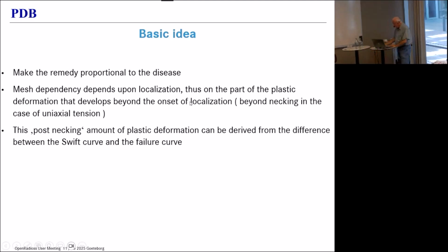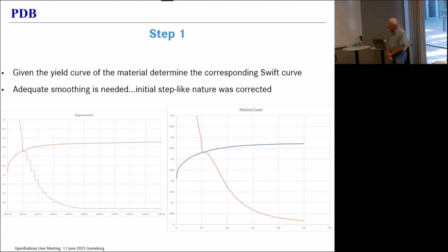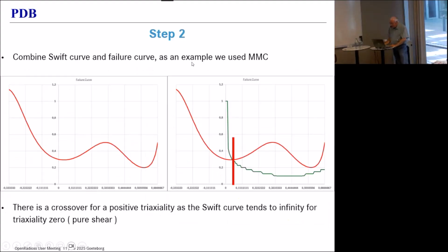So that's a very simple process. In step one, we take our yield curve and we take the derivative. We have to smooth that out a little bit. In step two, we compute with the process that I previously described, the instability curve, which is the green one. We're going to have to smooth that one out a little bit too. And we combine that with the failure criterion, which can be anything. It's the red curve here. And in this case, that was a modified Mohr-Coulomb, but it could be anything. It could be something that you tabulated from experiments, wherever you get your failure criterion from. And you see that the two curves cross over for some positive triaxiality. Now my triaxialities are positive in tension the way they should be.